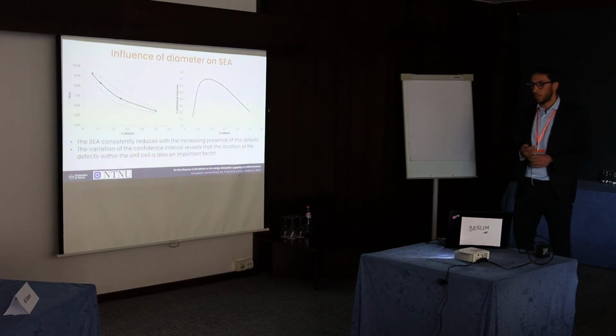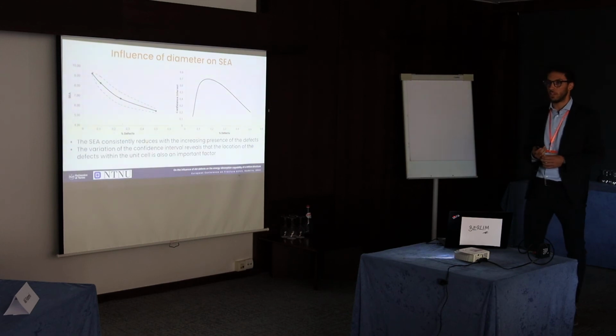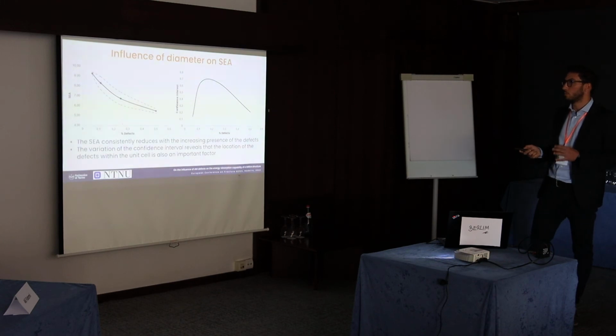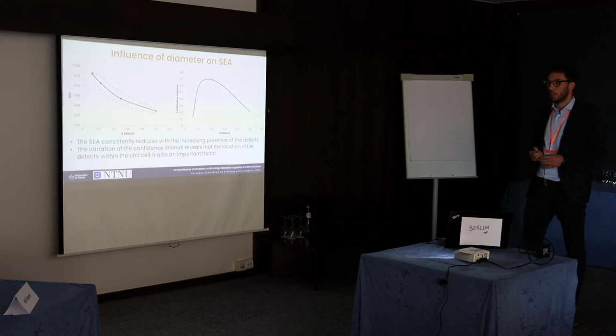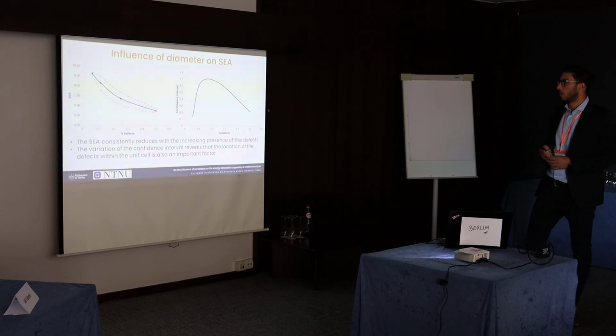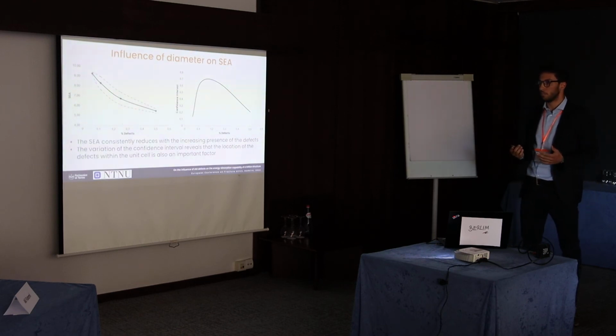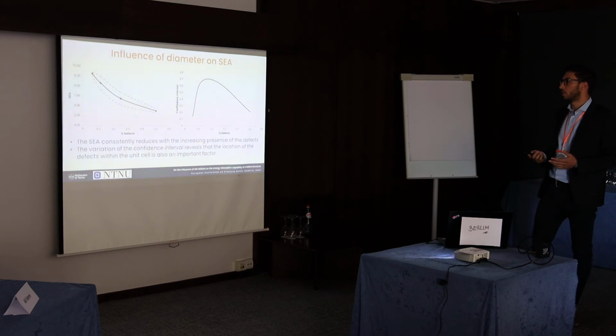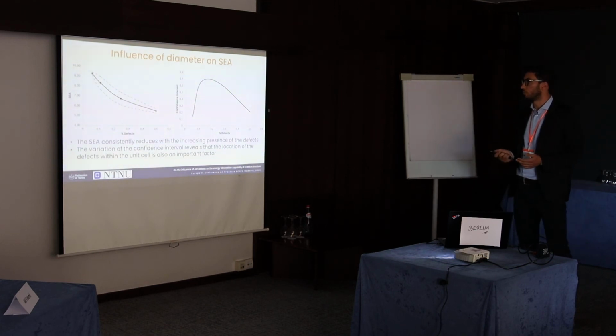And this can be explained by the fact that the location of the defects is also an important factor. Indeed, when we have a small percentage of defects, the pristine material can compensate for the presence of the defects, and so the location is no longer an important factor. And similarly, at the other extreme, the defects are dominant over the pristine material, and so the location is no more important. While in the middle range, the location of the defects is an important factor.